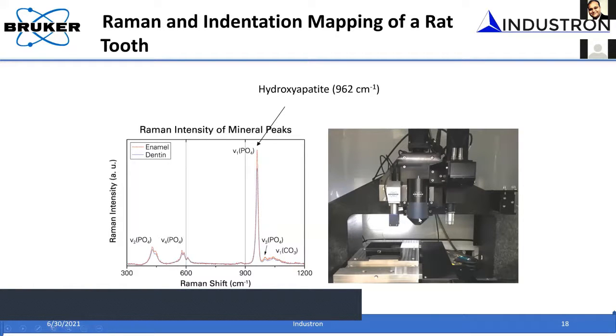Now, along with this mechanical measurement, if you bring the sample under this Raman microscope, we can measure the Raman peak intensities. For example, if you have hydroxyapatite, you will see a peak at about 962 per centimeter. If you look at this peak, and you know this is due to hydroxyapatite, and you measure the intensity of this peak, that gives you the mineral content. Now, we have a way of understanding the chemistry of the surface. If you have a high mineral content, can you correlate it to the mechanical property?